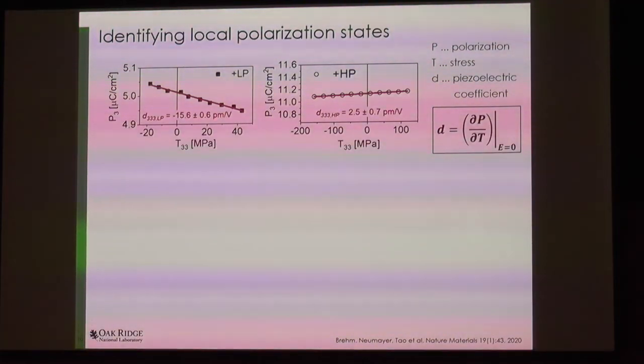Whereas for the high polarization phase, now we basically end up with a 3D crystal. We get less stress dependence, translating into a smaller piezoelectric coefficient, and it is positive. So that's very different, and we should be able to see that in piezo response force microscopy.